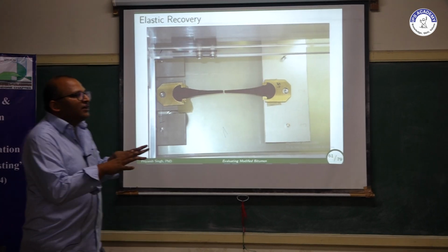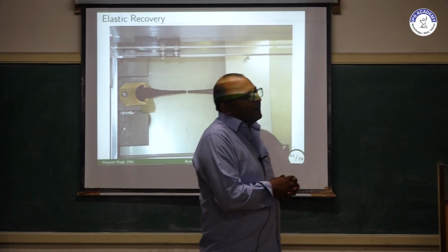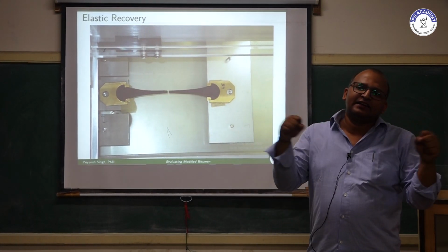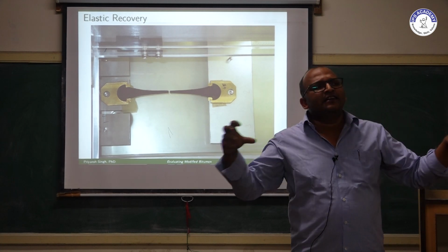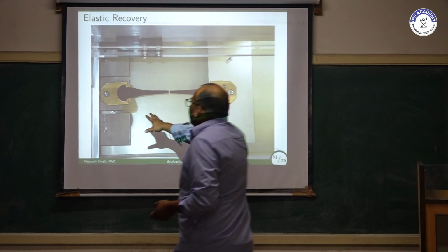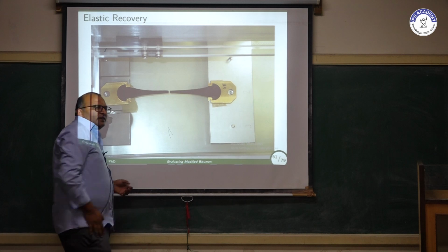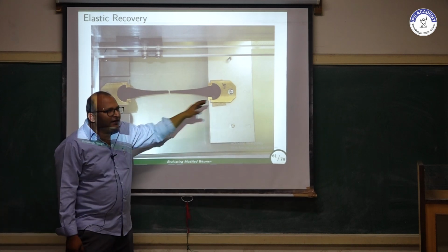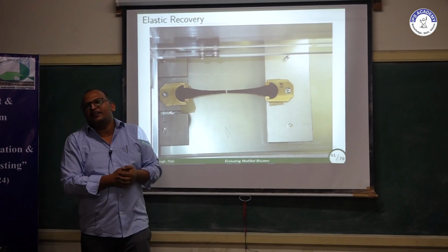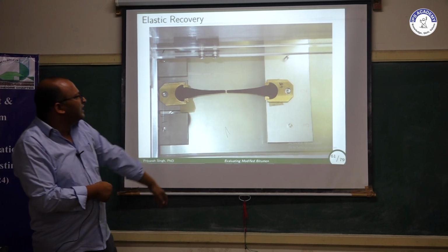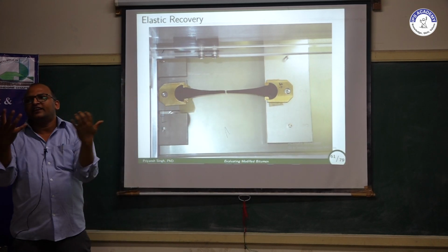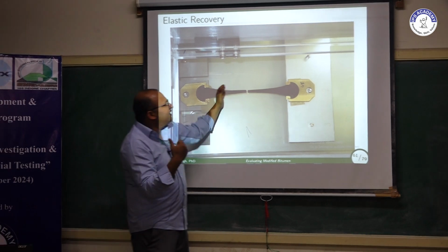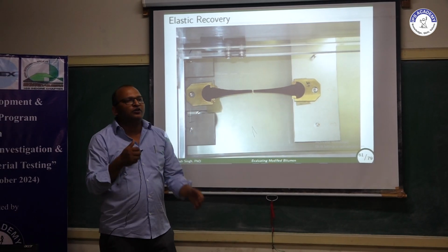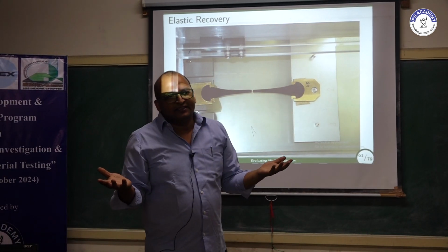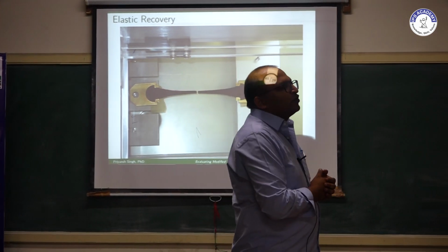The next test on neat binder, which we will do for polymer modified binder or any modified binder, is the elastic recovery, similar to your ductility test. Here we will take, but this briquette is different actually. So we will take our binder in this briquette and we will stretch it to 15 centimeters of distance, and after that we will cut the binder. Now if there is elastic property, it will try to regain its shape. We will check what percentage of shape is regained by this binder, and that will be known as the elastic recovery.